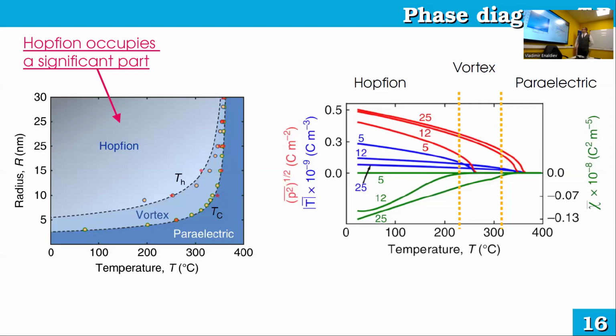Also, we have some polarization characteristics for specific nanoparticles. It's interesting to note here that people often use this thing, vorticity. It's just the rotor of P, and they use it as some kind of numerical evaluator for different complex topological states. But please note that this vorticity turns to 0 with polarization. So basically, when you get to the paraelectric state, both the square magnitude of polarization and vorticity get to 0. But what is interesting, the chirality indicator vanishes before the phase transition. It vanishes when Hopfion transforms to vortex. So it's pretty good to keep in mind if you analyze such systems. There are very different indicators, and vorticity is a bad indicator if you want to distinguish some complex transitions.